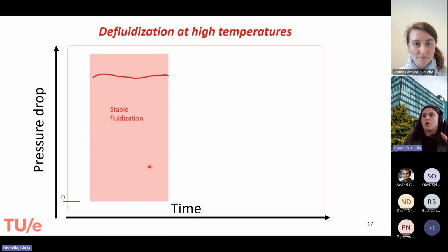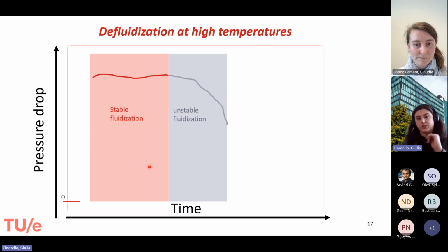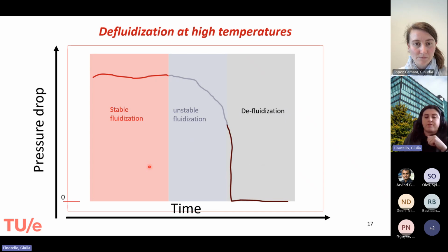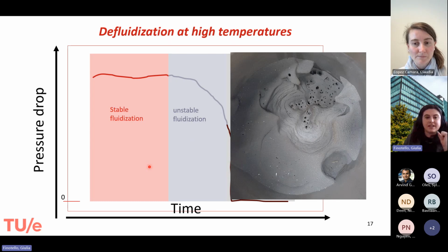And so what we usually do in the fluidized bed is looking at the pressure drop over time, so the pressure difference over our bed. And if everything goes well, we have a stable fluidization. If something starts to go wrong, it means that we are experiencing some sticking, and we see a certain drop of unstable fluidization until we see a very fast drop, and that's where we reach defluidization. In this situation, it means that our bed is not moving at all. So it's actually something looking like this.